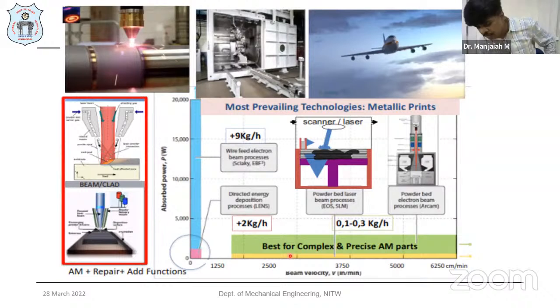The WAAM process or the DED process is the fastest process, which can fabricate highly complex parts, even at 9 kg per hour, and with powder feeding, around 2 kg per hour, with the direct energy deposition process, LENS or DED or the laser concept.